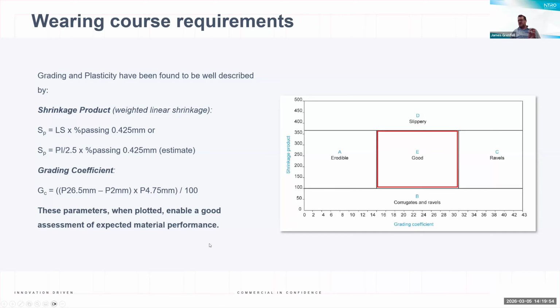So what does that mean? If we divide that chart up into quadrants, we know that unbound granular materials tend to perform quite well if we can make them fit within this good area on the graph. If they are higher on the grading coefficient side, they're potentially at risk of ravelling. If they're low on the grading coefficient side, they're at risk of being erodible. If the materials are higher on the shrinkage product side, they're likely to be at risk of being slippery. If they're low on the shrinkage product side, they're likely to corrugate and ravel. So this chart now gives us an extra way to try and define how our materials might be performing in the field.